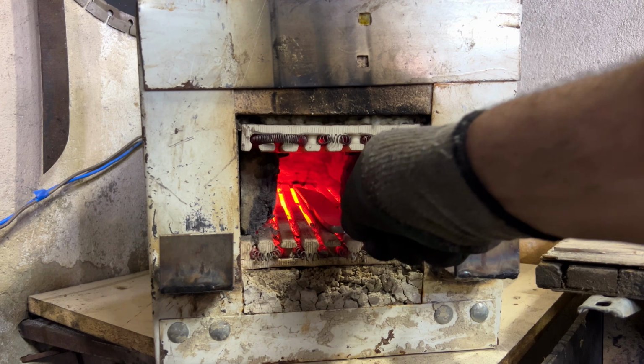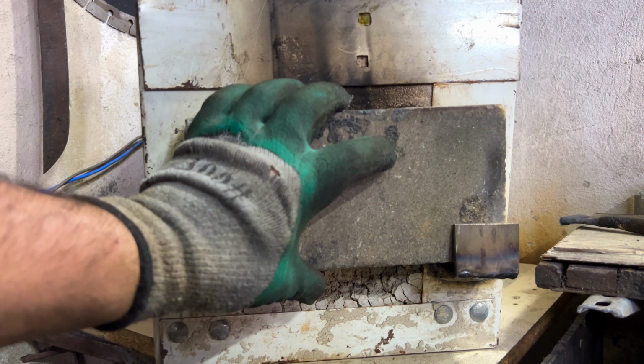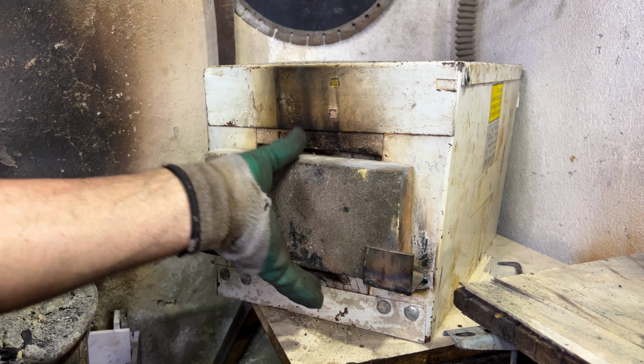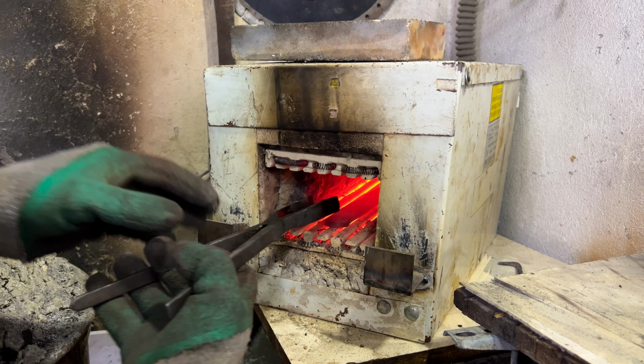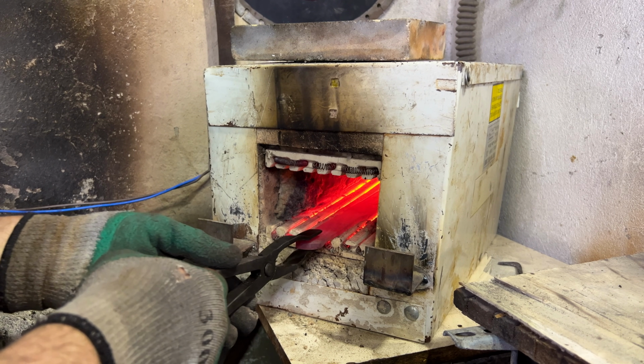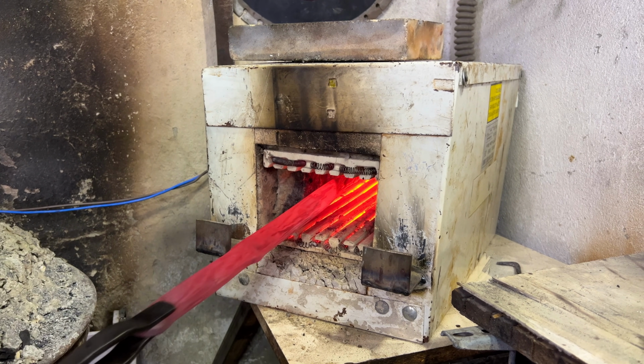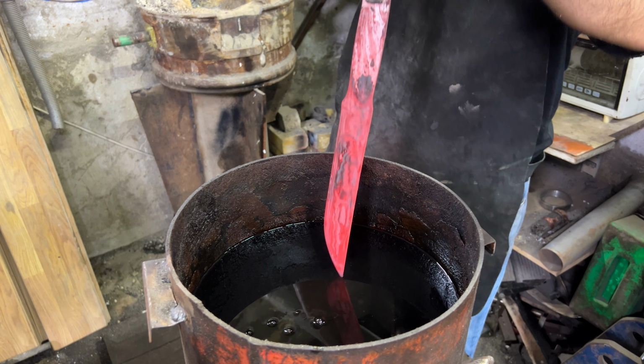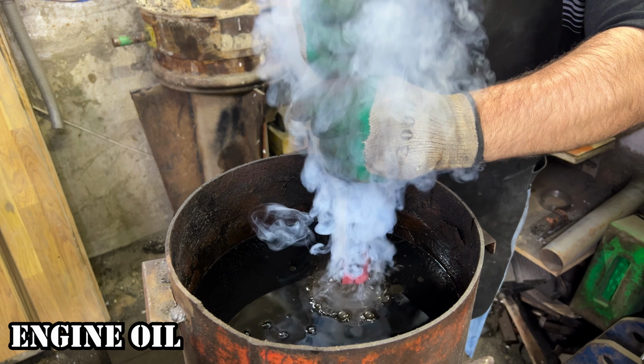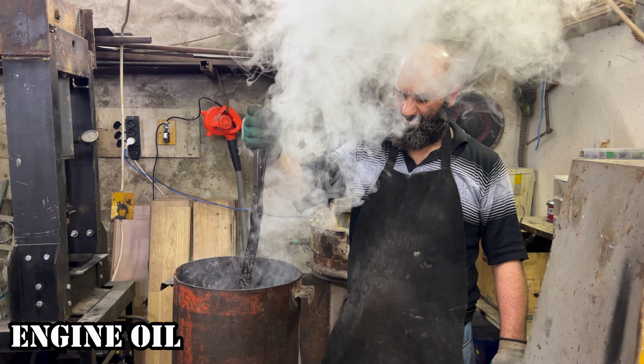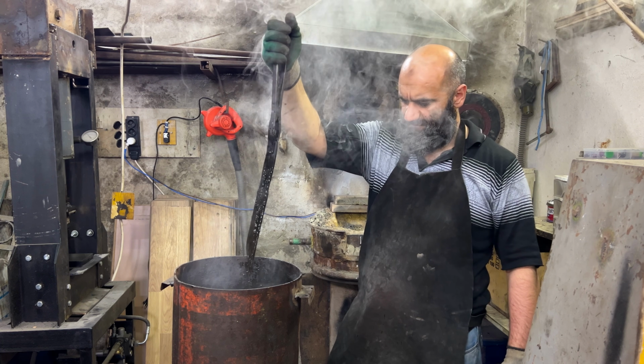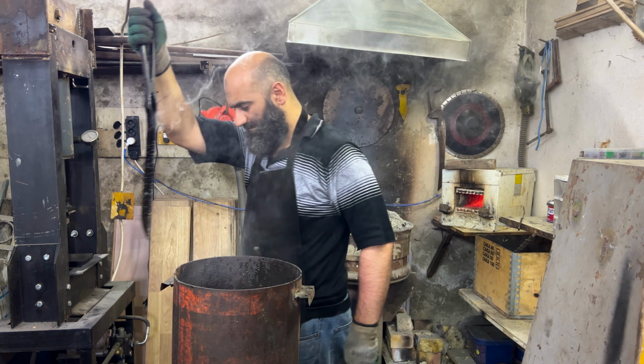The moment of truth, the quench. I heated the blade to critical temp, non-magnetic, about 800 Celsius, and dunked it in oil. This freezes the crystal structure, making the steel hard. If it doesn't warp, or crack, or ping, we win. After quenching, it's brittle, so I'm putting it in vermiculite to cool down slowly or temper it slightly to relieve stress.